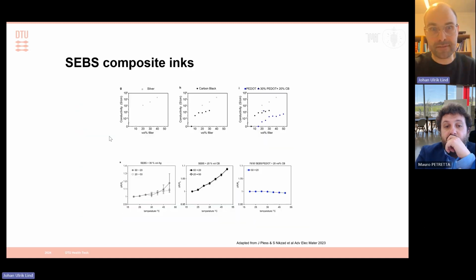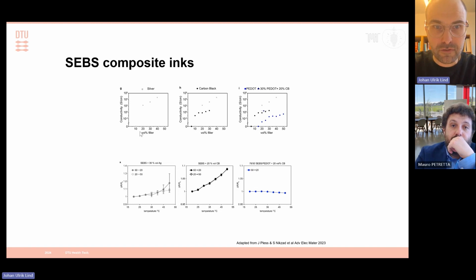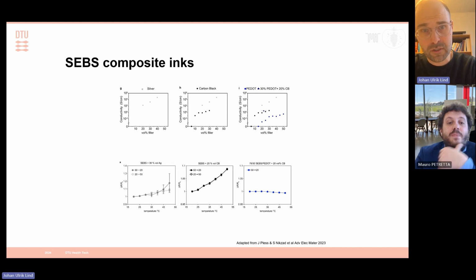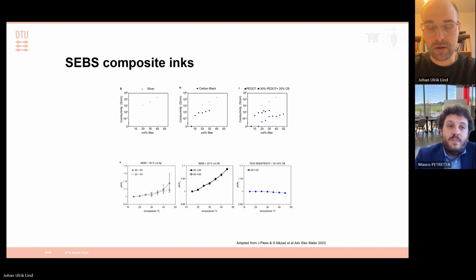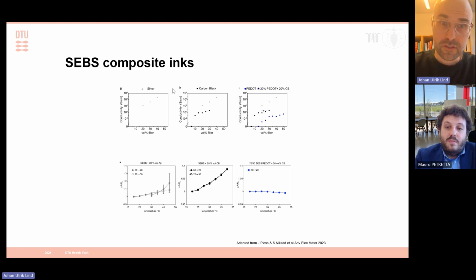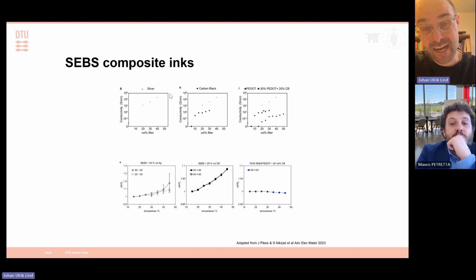We looked at how much volume content of filler. In this case, the filler is the conducting particles. And when I say volume, this is the volume of the final composite. So remember, in these nail polish based inks, there's a large fraction of carrier solvent. So we start out by making, say, a 20 volume% solution of the polymer, and then we add particles to that. And then in the final composite, we can easily get up to, so this is for silver particles, here's plotted up to 40%, and we just look at the conductivity. You can obviously get higher. We can get at least up to 60% volume fraction of conducting particles in this particular system.